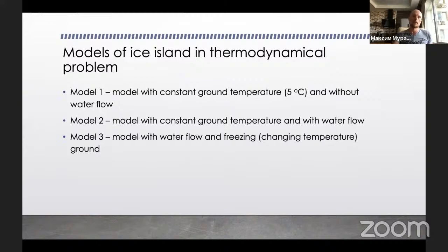We study three models of ice island for thermodynamical problems. First model doesn't take into consideration water flow and has constant ground temperature, which is equal to 5 Celsius degrees. Second model is a model with constant ground temperature, and it takes into consideration water flow. Model 3 is a model with water flow and with freezing of ground. So it takes into consideration also the change in temperature of ground.